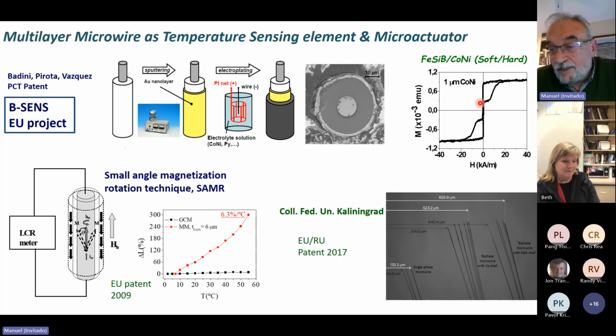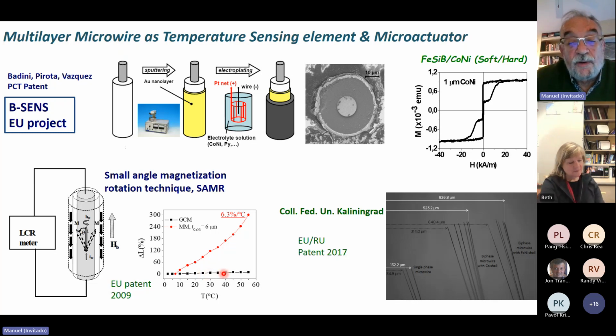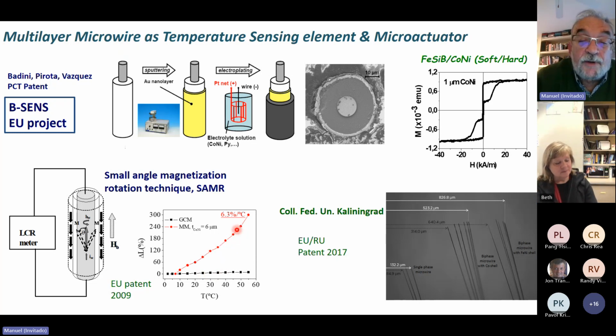You see there are two large Barkhausen jumps that are caused by the reversal of magnetization in the soft phase and in the external hard phase. So we have used this type of microwire for several applications. I would like to mention some making use of the small angle magnetization rotation technique, which is a classical technique. We can determine the change of the inductance of the microwire as a function of the temperature. This was in connection to some application related to temperatures close to that of the human body. You see that there is a large change of the inductance in the interesting range of temperature.